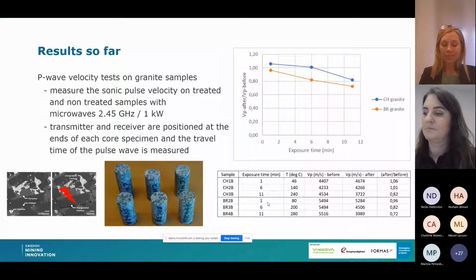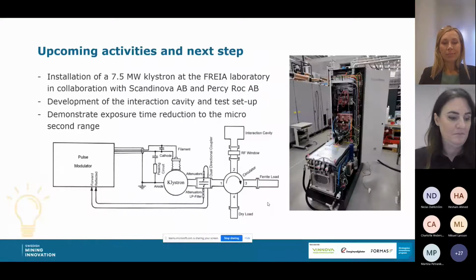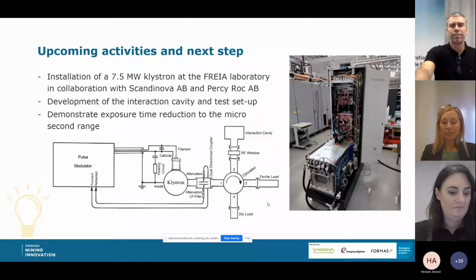So the upcoming activity is to use a klystron, which is a very high power microwave source. That's coming from ScandiNova, and then to put in place a test setup with that device and to realize very fast exposure, we talk about microseconds, to very high microwave power, to induce cracks in a fraction of microseconds.